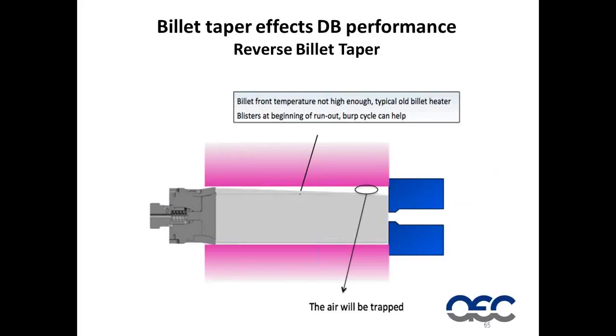Unfortunately, many of the old billet ovens give us a reverse taper, in which case the die end of the billet is actually cooler than the dummy block end of the billet. In these cases, we actually get a reversed upset, so the billet will actually start to deform or crush at the dummy block side towards the die end. Unfortunately, the dummy block can't help with this type of a blister, and the only way we can get rid of this air is through the burp cycle.